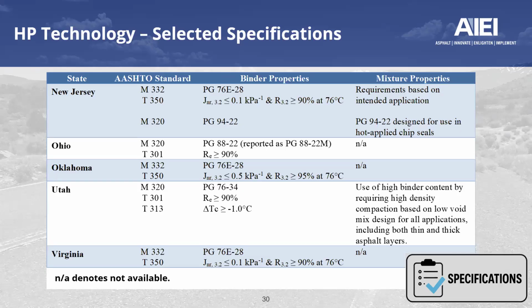Yeah, maybe the only thing to add is to echo what Dave said, it depends on the state need. If we take a look, for example, at Oklahoma, they do have a 95% and not a 90%, but their non-recoverable creep compliance is at 0.5, which is typical for other states and not necessarily an E-plus or E-plus-plus or an HP for what the other states require. So again, lack of standardized definition and various specs, tailored to whatever need the state has.